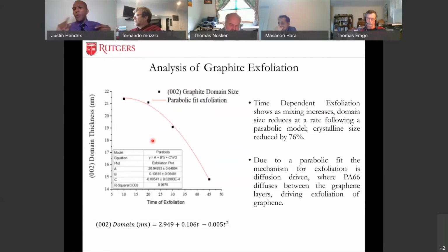Now, one of the caveats to talk about, in which we went back and forth, is how much graphene do we have in it, right? And actually, we'll see that we have a lot of graphene that's below that 14 nanometer mark. And that 14 nanometers is more of an approximation, right? Graphene being very, very small will ultimately be eaten up by the background of the X-ray. We'll see examples of this using interfacial characterization methods, that we actually have a plurality of graphene flakes in there. And as I said, this is a general approximation.